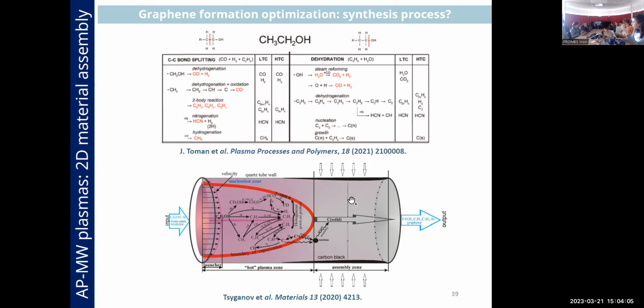The amount of graphene depends on the plasma gas temperature, as I said before. Why? Because there are two different ways of decomposing ethanol molecules, and the gas byproducts and also solid byproducts depend on whether we have high temperature plasma or low temperature plasma. So these results that were found by other authors are in agreement with what we have found from an experimental point of view.